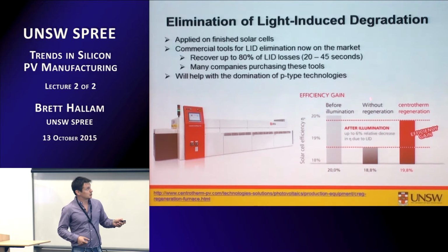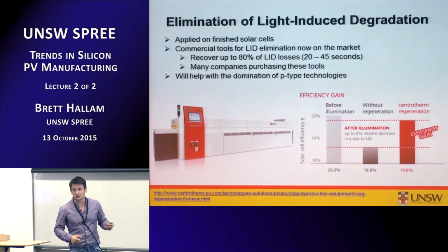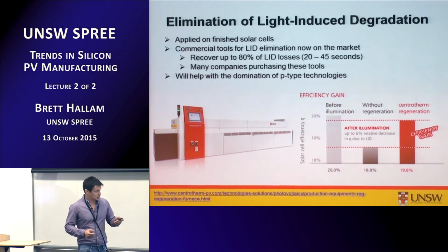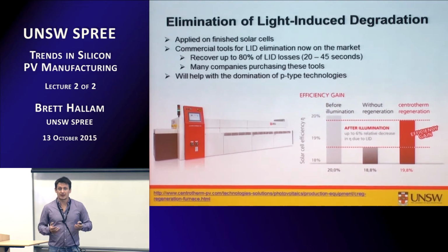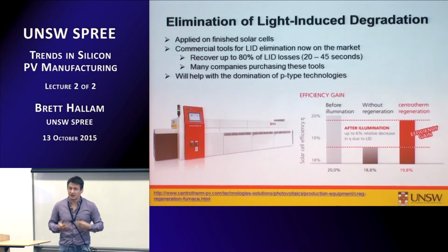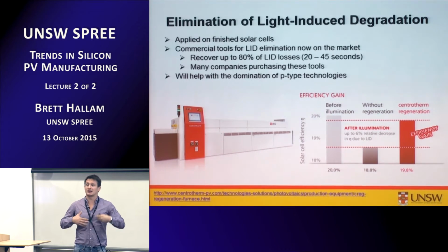So if we take a normal solar cell, this is a PERC solar cell, 20% efficiency, 20% straight off the production line. You put it under sunlight, it drops down to 18.8% efficiency in this case. But there's a process with illumination and a temperature where you can recover permanently most of that efficiency loss. So we can eliminate a lot of the LID losses.